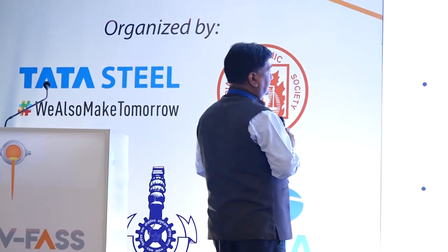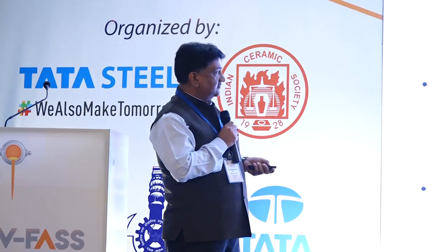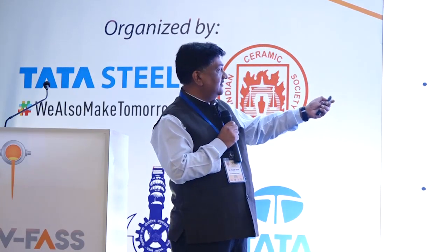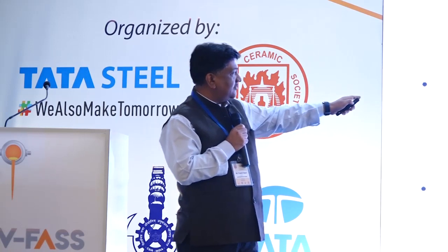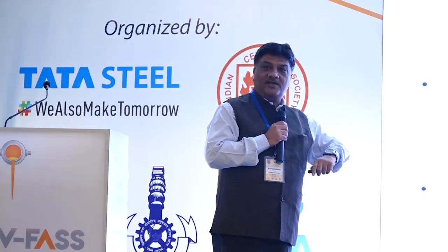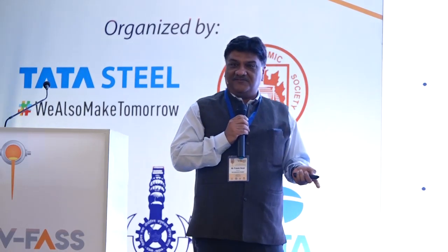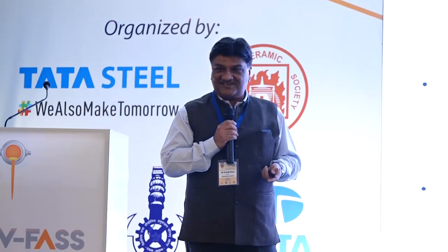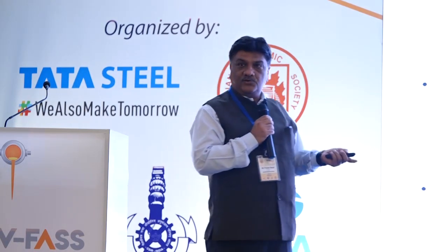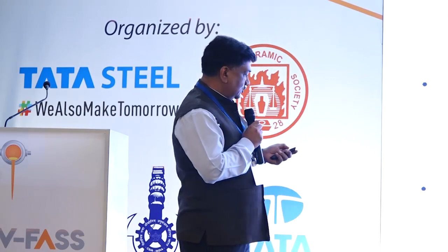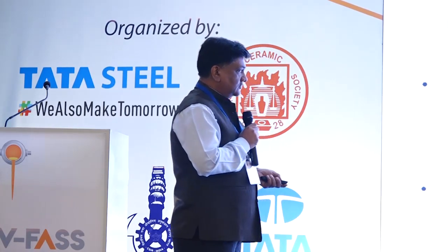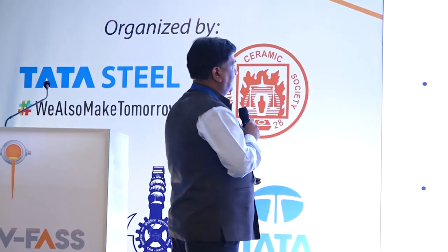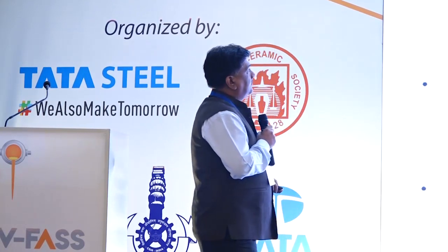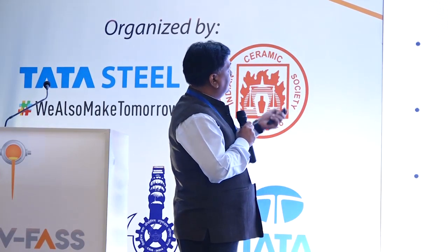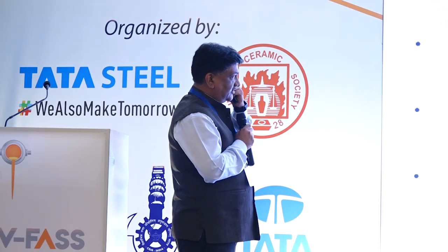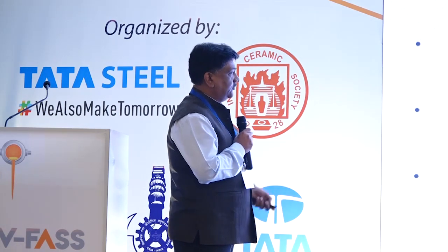Pond ash and bottom ash, we made an attempt to use it. Here is the change required. In the IS 383, we mentioned bottom ash from thermal power plant. Why bottom ash from thermal power plant? We have a good quantity of bed ash from Tata Steel also. Those can be utilized for the same, maybe from other sources. This can be done. So we made an attempt to replace up to 25% with this bottom ash. These are the data, of course, from the Tata Long Products at Jamshedpur here.